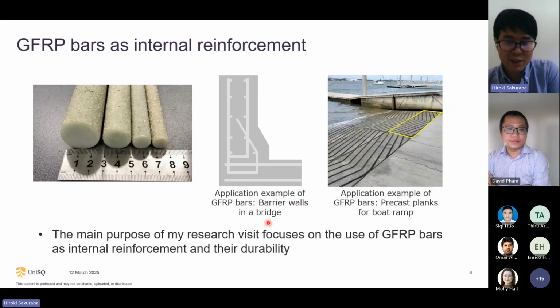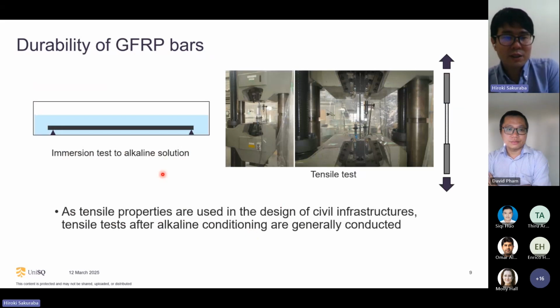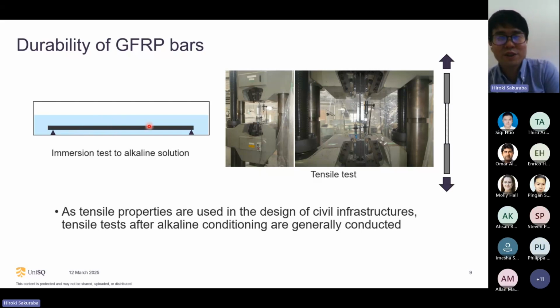So far I have studied this kind of GFRP bar durability. To study the durability of GFRP bars, we normally investigate tensile properties, because tensile properties are used in the design of civil infrastructure structures. So tensile tests after alkaline conditioning are generally conducted. For example, we use bare bars normally, and we put the bars in alkaline solution. And after that, for example, 60 degrees Celsius for 90 days, we conduct a tensile test. So we will know the durability of GFRP bars by conducting an immersion test and a tensile test.